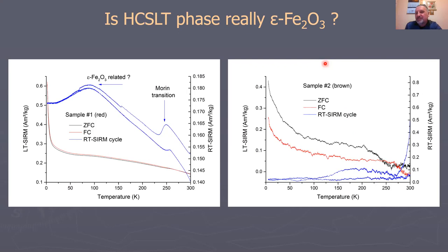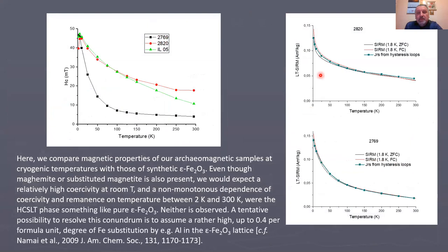Okay, now we can also compare the results of our archaeomagnetic samples directly with known data for synthetic samples using the hysteresis measurements at cryogenic temperature. We did that for a few samples, and for all of them, we see just a monotonous decrease of coercivity between 5 Kelvin and room temperature.